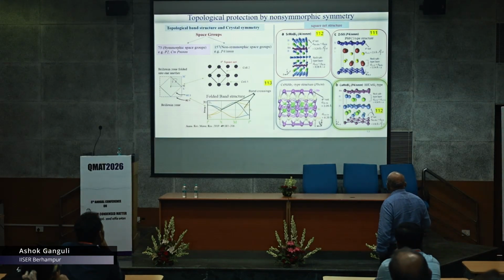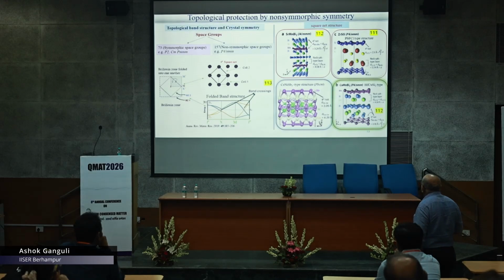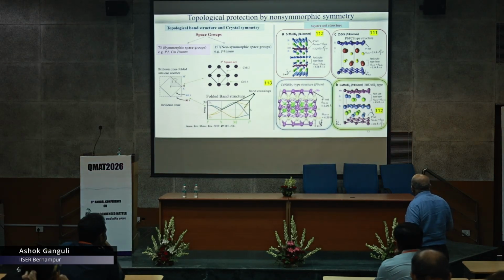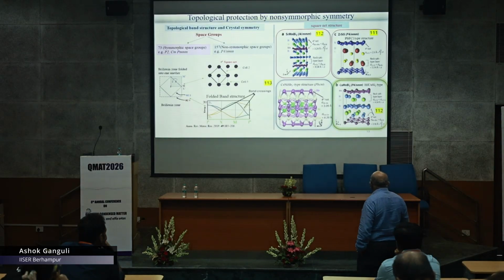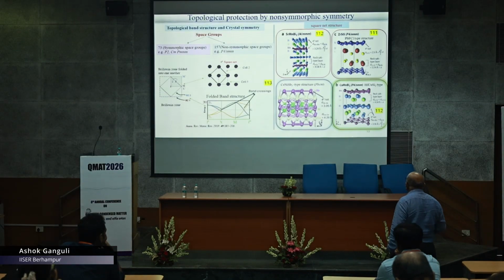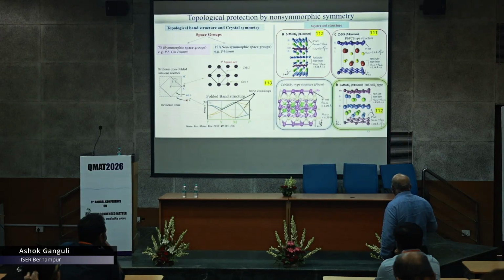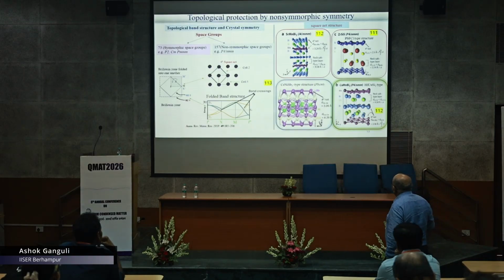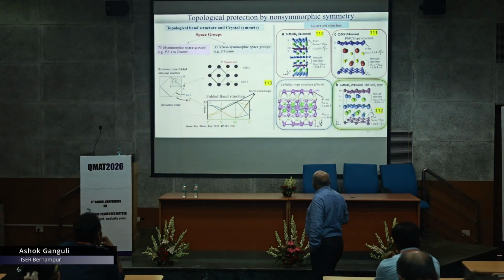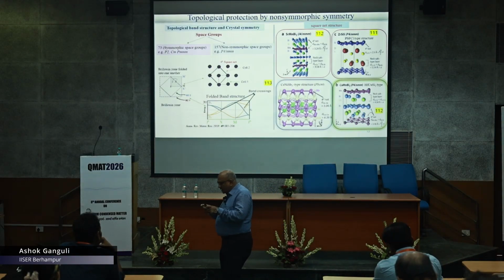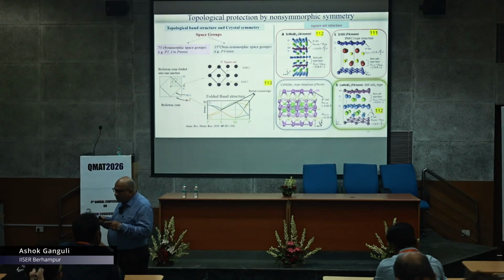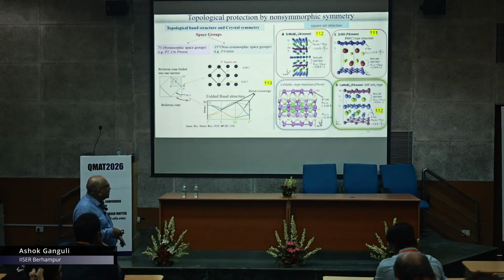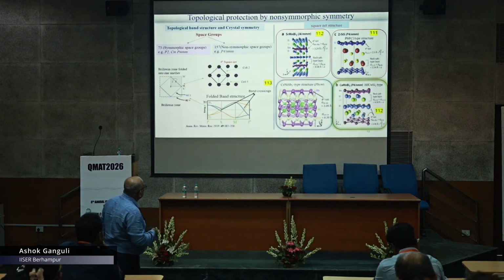And in this 1,1,2 structure, again, you have rock salt layers, and in between and on top you see this planar structure. Here in the plane you have manganese, and you can change it for different species. This is 1,1,2, this is 1,1,3, so an additional layer will come. And of course, these distances are also very important, that you are matching the top layer with the rock salt layers inside, so as to cause less distortion.